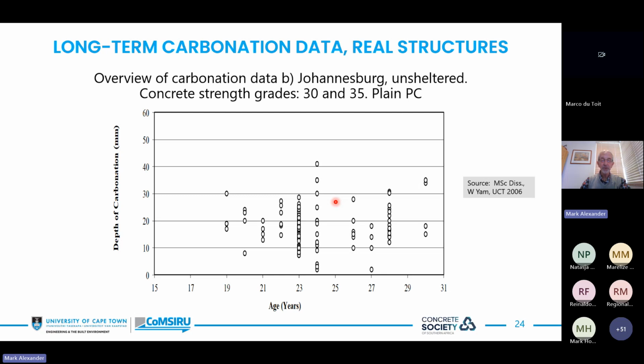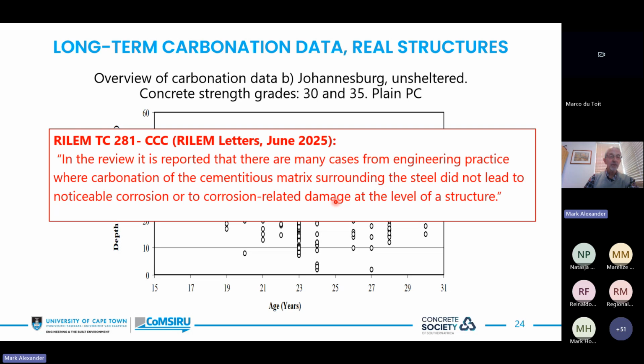It may well be so, of course, in the low carbon binders, but then we've already had caveats in regard to that matter. So RILEM, in a very recent RILEM letter in June 2025, had RILEM TC281, which is around carbonation, had this to say. In the review that is in this report, it is reported that there are many cases from engineering practice where carbonation of the cementitious matrix surrounding the steel do not lead to noticeable corrosion or to corrosion-related damage at the level of the structure. Go and read that report if you want to see some more.